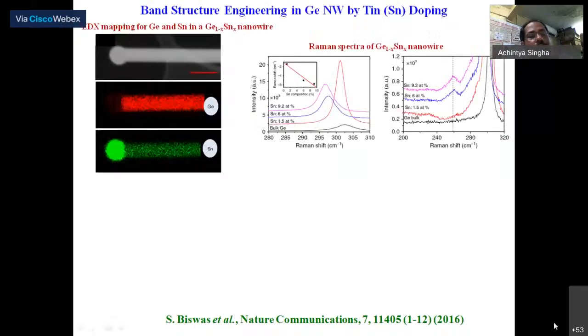So here's an example of germanium doped with tin. The idea of this work is that germanium is an indirect band gap semiconductor, and if you can change the indirect semiconductor to a direct band gap semiconductor, that would be a great achievement, because the photonic application of direct band gap germanium is huge. So the motivation of this work was to get direct band gap germanium nanowire by tin doping.